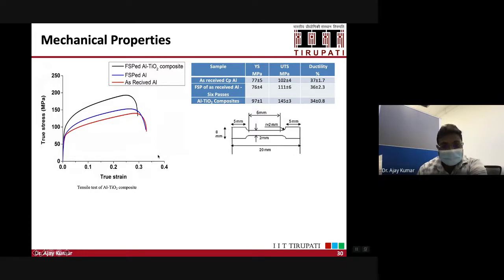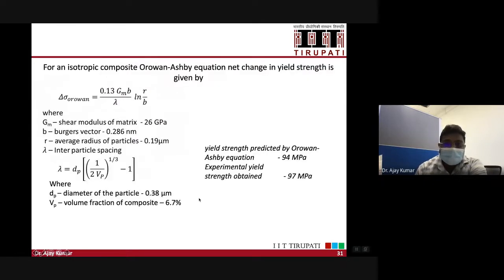So this type of mechanism we have developed to make these nanocomposite materials, and we got similar results in these composite materials, where you have high strength, high yield, as well as high toughness. We have also verified the experimental results with the theoretical model, and we have seen that the yield strength predicted by the Orowan equation and the experimental yield strength are almost the same.